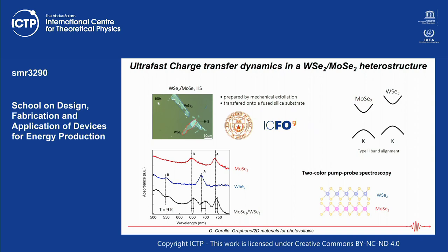Q: What pump power is used in these pump-probe experiments? A: We try to stay in the so-called linear regime, using as low power as possible, but we need to detect the signal. Typically we're talking about fluences on the order of microjoules per square centimeter, so the densities of charges put into the material are not very high.